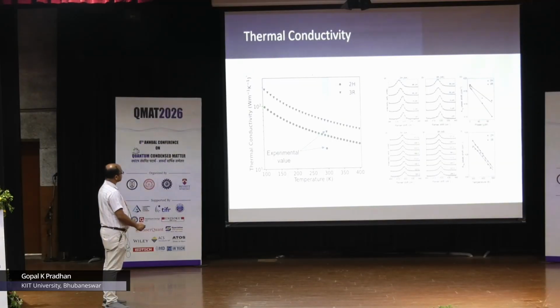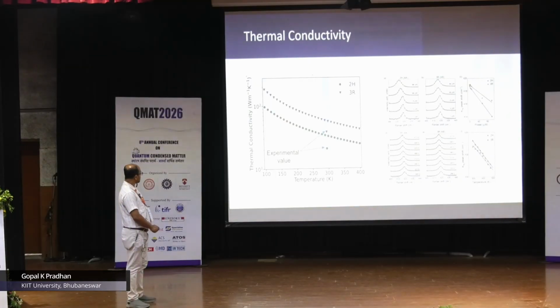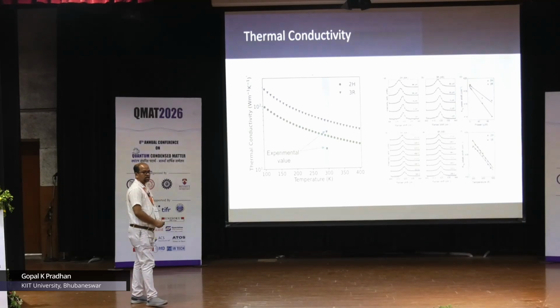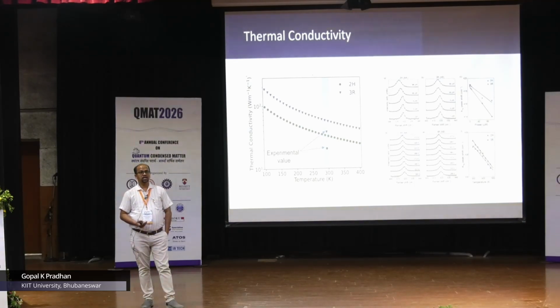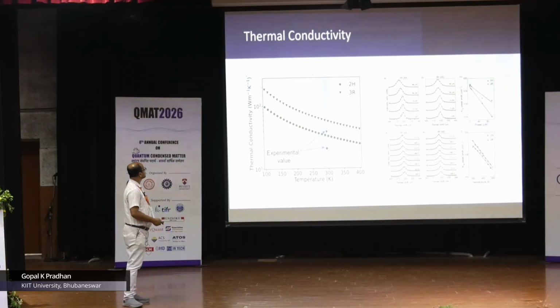This is the thermal conductivity, and this is what people have actually measured using MEMS and other techniques. So, it is not that bad, but it looks slightly overestimated for both the phases. What I want you to appreciate is that we are still able to capture, using a simple technique like Raman scattering, and measure the thermal conductivity of these kinds of systems.